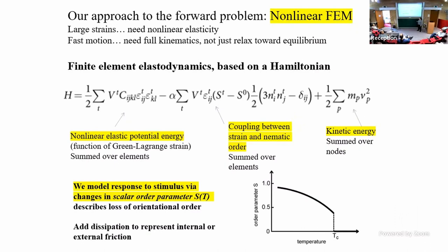The other issue is there's more than one way that these materials respond. If we're just shining light on it or just changing its temperature, the internal stresses are not that big. So my assumption is that the nematic director just rotates with the body and doesn't otherwise change. However, if you start with the material, for instance, nematic director north-south in a liquid crystal elastomer thin film, and you stretch it east-west, then you get stripes where individual regions of the material rotate left and right if it's really hard clamped on the sides.